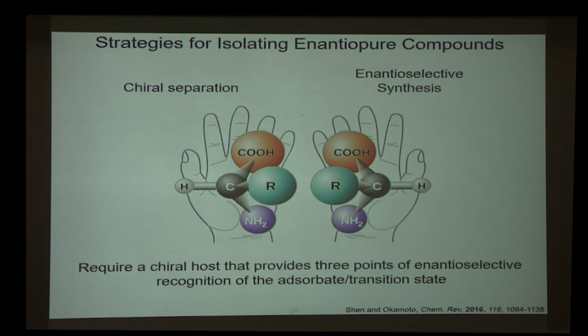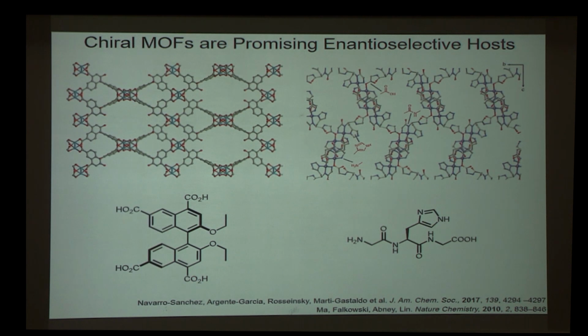Regardless of which strategy you select, what's needed is a chiral host that binds enantioselectively either to an adsorbate in the case of a chiral separation, or a transition state in the case of enantioselective synthesis. And chiral MOFs are quite interesting targets to utilize as hosts for these applications. This is because of the fact that they have these tunable three-dimensional cavities. And indeed, there are some successful examples in the literature where chiral MOFs have been used either for chiral separations or enantioselective synthesis. I'm just showing two examples here, along with the organic building blocks that went into the materials.